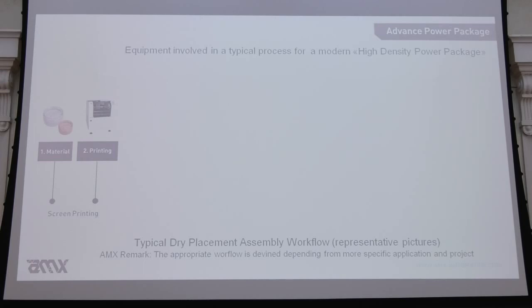Here we have the classic, let's say, production workflow scenario. So obviously you choose the material based on the metallization of the substrate and the backside metallization of your die, silicon or silicon carbide. You apply the material using stencil printing, nozzle dispensing, any kind of method. Anyhow, you place the paste on top of your substrate. We have a pre-drying process, roughly around 120-130 degrees Celsius. Anyhow, lower than 150, because at 150 the sintering starts.